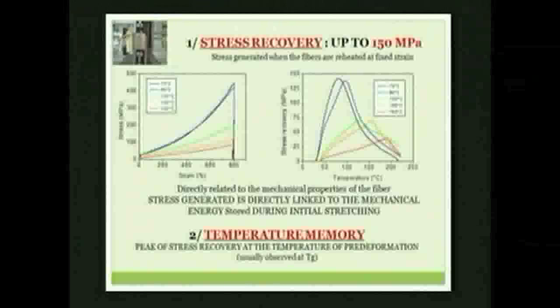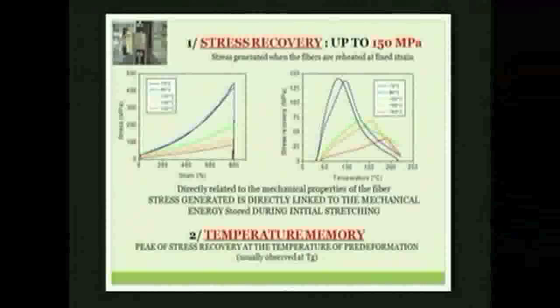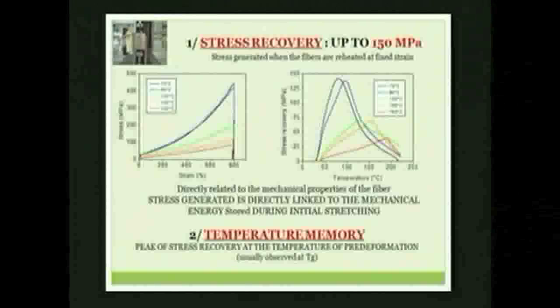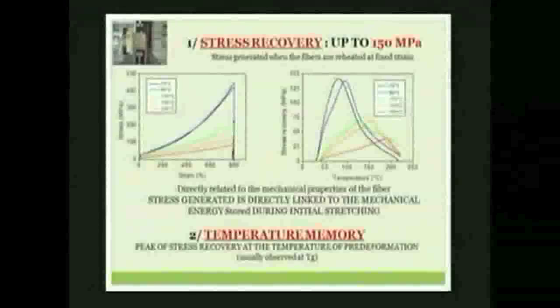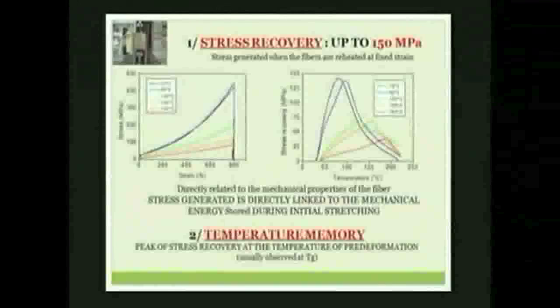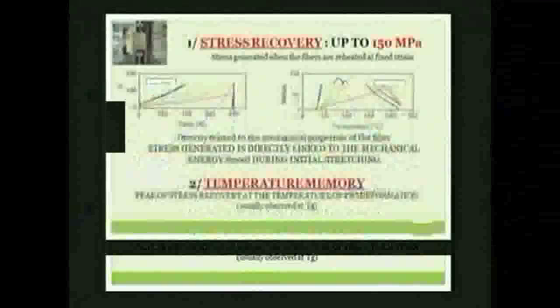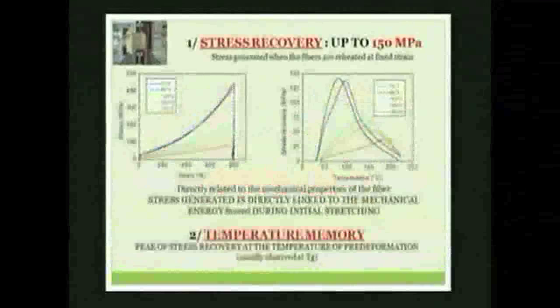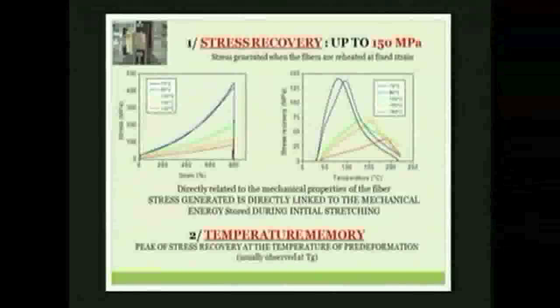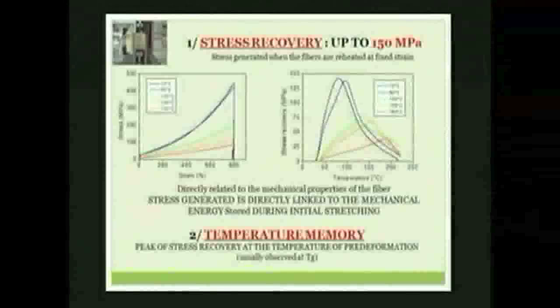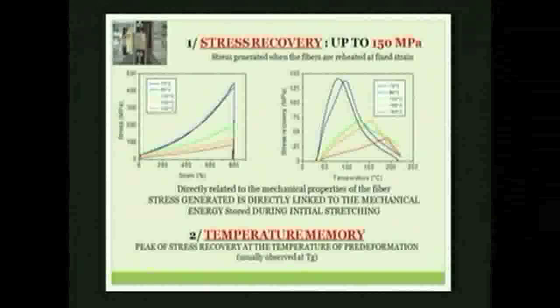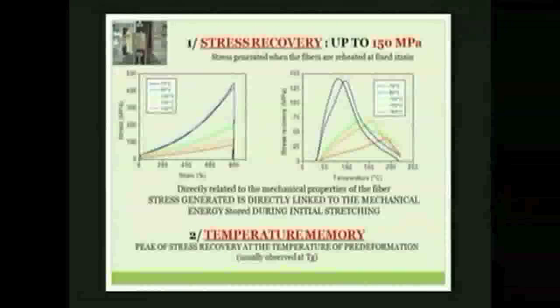And we also observe something very particular that has not been observed, to the best of my knowledge, before, which is a temperature memory. The maximum of stress recovery that you get at the end is at the temperature where you pre-deformed the fiber. And normally you don't see this in conventional polymer. In conventional polymer, the maximum of stress recovery is always at the Tg, the glass transition of the polymer.